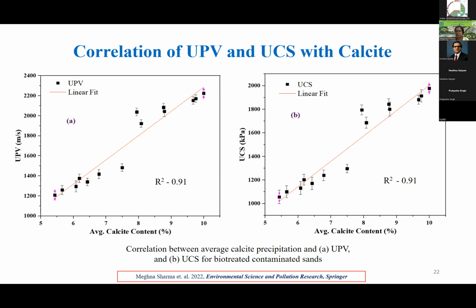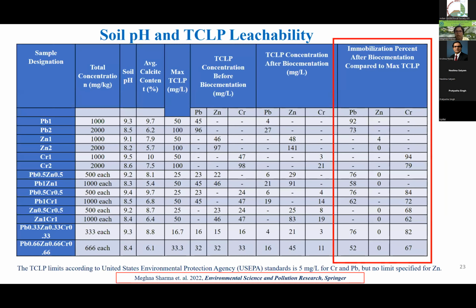It can be dealt with by different amounts of urea and calcium chloride dihydrate, as I said. Now, this is the toxicity characteristic leaching procedure testing, and initially we determined the soil pH, and as sir said, pH plays an important role. So if this range of pH can be achieved, it shows that calcite precipitation was achieved in the soil media.